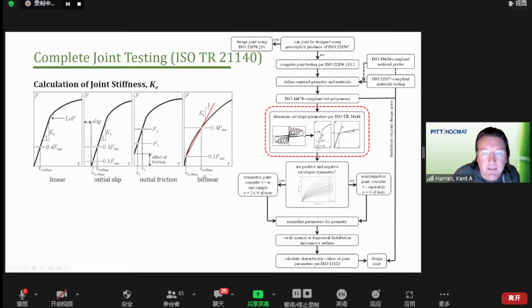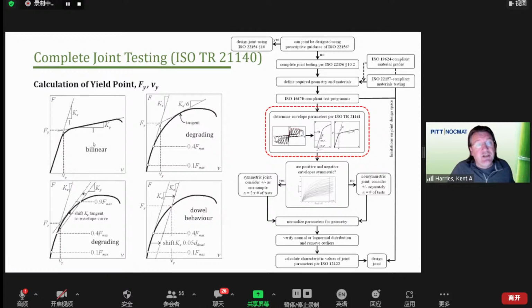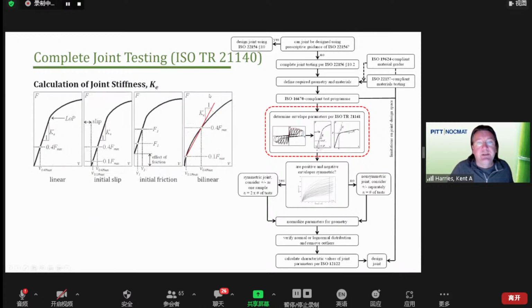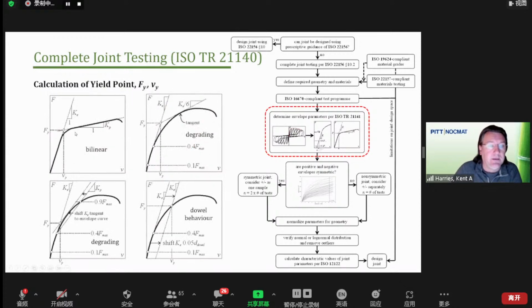And similarly, a bilinear behavior. And in general, what we're going to do is we're going to find that stiffness as the secant stiffness between, and rule of thumb is 40% of the maximum and 10% of the maximum. It doesn't have to be that, but that's the guidance. In addition, so we find the initial stiffness in this manner. We then find the post-peak stiffness, based again on the nature of the curve that we see.